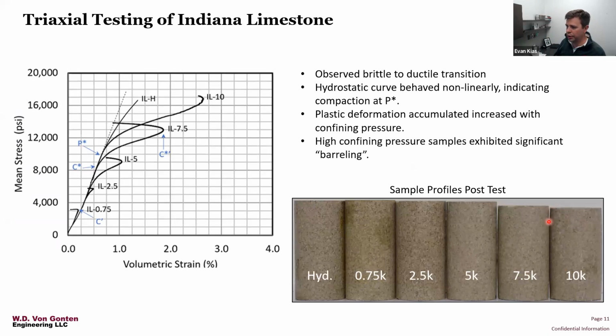It harkens to our assumptions of what the volume strain is in the sample. In cases where barreling is occurring under extreme confining pressure, the volume strain we report by assuming the sample is deforming cylindrically will overestimate the actual volume strain. This changes our quantification of how much volume strain is actually occurring.